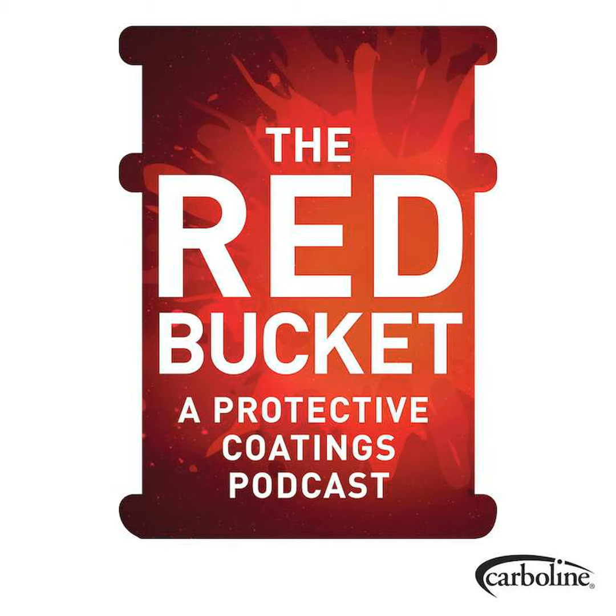When do we do it? Well, there are several methods that people go about. One is to get a fast set primer and coat it when the concrete temperature becomes stable or starts to decline. And then sometimes there's a chemical reaction going on in the concrete that none of us know about, and I've seen it happen. Yep. And it could be from below the concrete. But we should plan on always priming at a minimum when the concrete temperature is stable or descending.